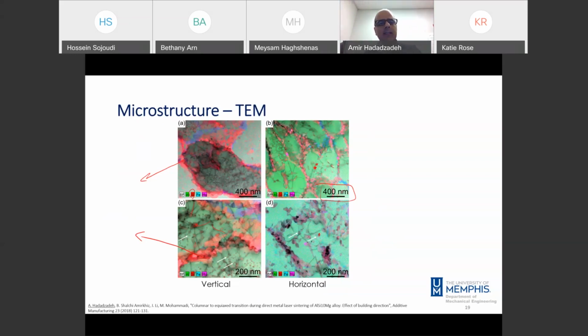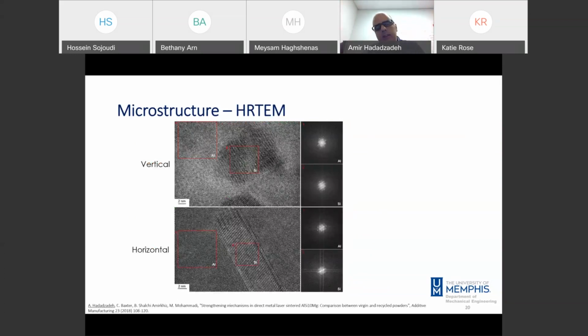That network of dislocations is called a pre-existing dislocation network, which is a common feature in AM materials because we have rapid solidification, we will have evolution of residual stresses, and because of those residual stresses, these dislocations will evolve in the structure. And these dislocations are interacting with the silicon precipitates. For example, here we can see some details. They're interacting with them, and also with the eutectic silicon walls. For example, here the dislocations are interacting with the eutectic silicon walls.